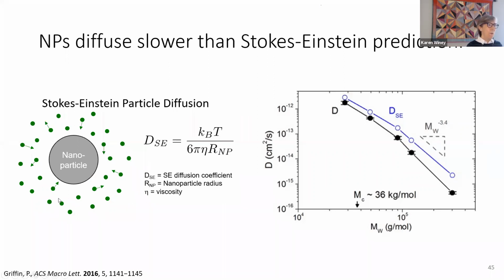And one of the underlying assumptions of Stokes-Einstein is that the fluid is interacting with the particle, or bombarding the particle in a Brownian way. Okay, so these green dots is not how I normally think of a polymer, particularly one that is adsorbed to the surface. Okay, so if we compare our diffusion coefficients relative to that prediction from the Stokes-Einstein, we see that our particles are moving a little slower.